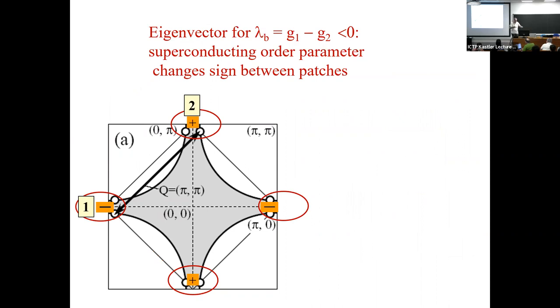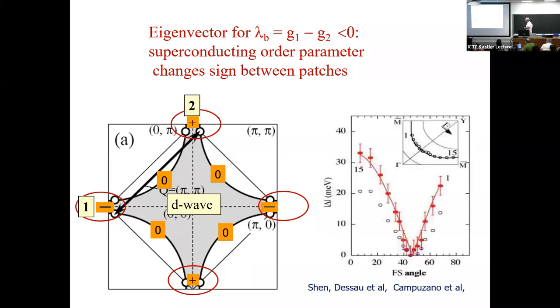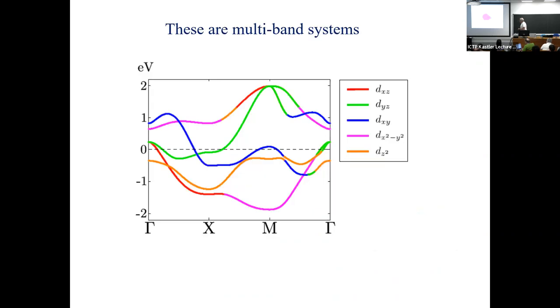So it's a sign-changing gap between patches, combined with the fact that k and minus k are the same point. Obviously, we have four points where the gap must go through zero on a Fermi surface. This is D wave. And again, without discussing cuprates very much, this is the work for which the Buckley Prize was given. ARPES studies of the superconducting gap don't show directly that the gap changes sign, but they show quite clearly that the gap goes to zero along the diagonal. Very good.